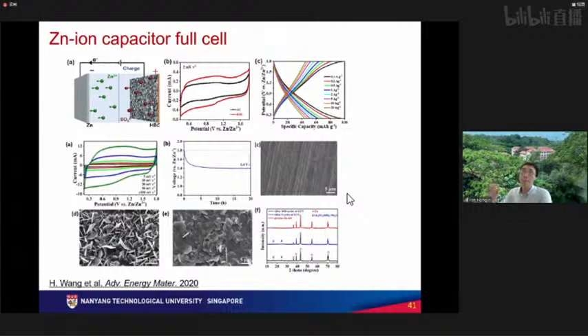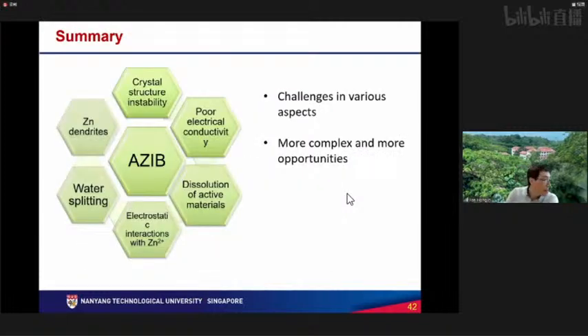And we want to say that there are some debates here about the working mechanisms. If you just use the mechanism from lithium and sodium capacitors, it's very simple. But if you look at some other papers I read, including those by Professor Liu Xihong and Professor Wang Guoxiu, they say that this cathode material can also absorb cations. Let's say during charge it can absorb anions, and during discharge it can absorb cations. So far this is not proven yet, really, it's kind of a proposal. But if it's really proven workable, this is a different mechanism.